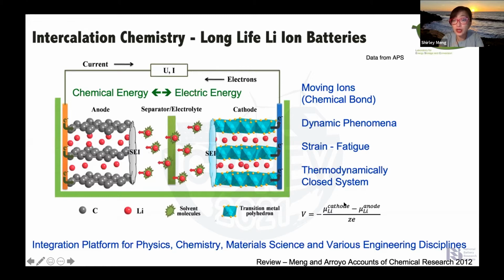So the thermodynamic Nernst equation is the best guiding equation to tell us why you have more than 4 volts in lithium-ion cells: it is because lithium, for example, has a very different chemical potential in the transition metal oxides versus graphite, right? So this is one of the important take-home messages.